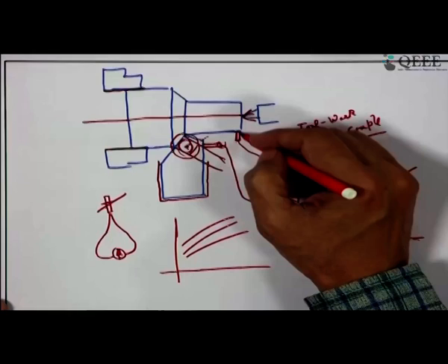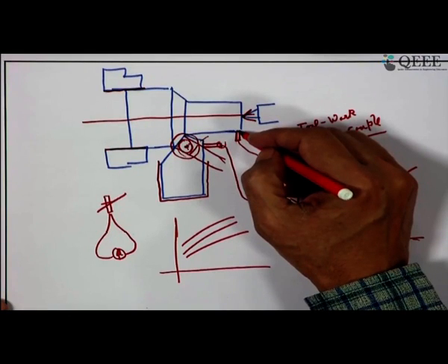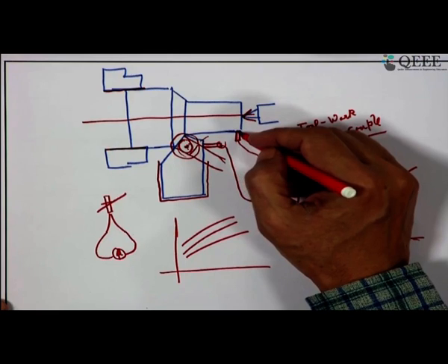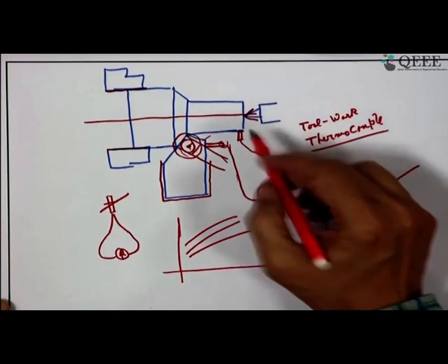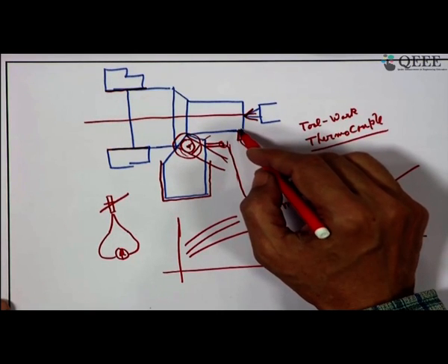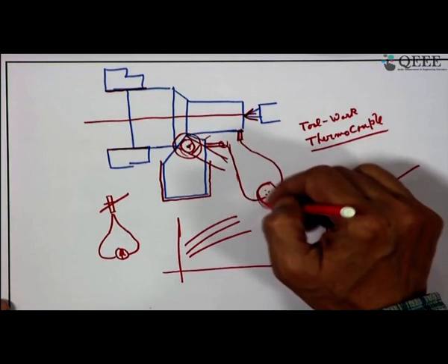Yes, sir. Okay. So, you can handle this thing in your laboratory if you like, using a carbide tool and then having one, just like I showed, a brush which will be a tapping point, a carbon brush. With that, and this will be a copper lead sufficiently long. So, this should not be too hot. With that you can have the millivolt reading here.